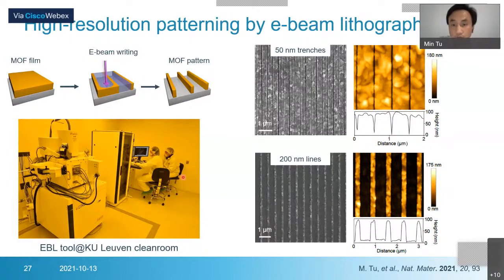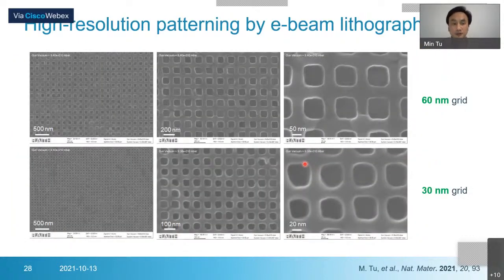And here is our e-beam tool. And we can see the 50 nanometer trenches. It's kind of a knife cut on the surface. Then we have the periodical patterns, and we can also have these lines. We also achieved very high resolution patterning by e-beam lithography. Here are some examples with this grid. We can achieve a 60 nanometer, 30 nanometer grid, and even a 30 nanometer grid, where it is not very regular because it has some proximity effects, and forward scattering and back scattering induce some non-uniformity, but you can still see it's kind of a periodical structure.